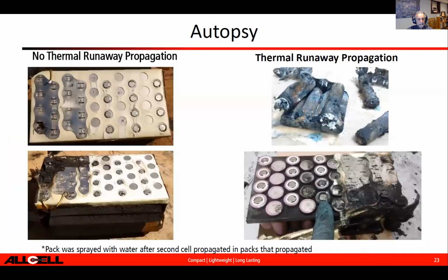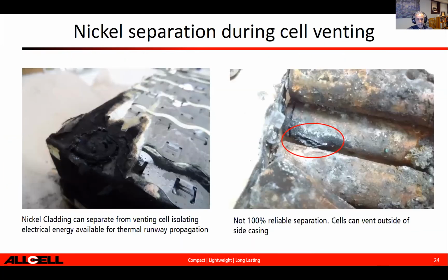Here's some autopsy. What you see is the pack to the left, which has phase change composite. Once we open it up, you can see that one cell fails, but the rest of the pack is fine, it's still intact. However, the one to the right, you see the domino effect, where we actually started pouring water after those cells propagated, so we could stop it from going further. And then you can see here that some of the cells are really charred after that thermal runaway.